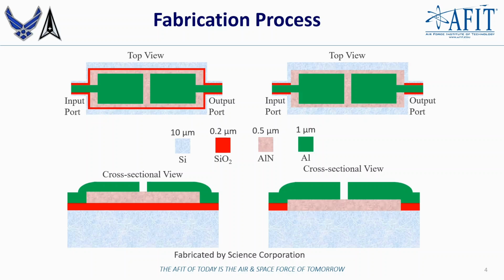In both cases, 500 nanometer aluminum nitride layer depicted in pink is used as the electromechanical transducer layer, and the aluminum electrodes are shown in green. The silicon dioxide layer serves as an insulating layer and also plays a crucial role in acting as a buffer layer, smoothing the surface defects and enhancing the bonding between silicon and aluminum nitride. This helps to enhance the device quality factor. All the structures were fabricated using CMOS compatible processes at Science Corporation, making the technology scalable for larger application.